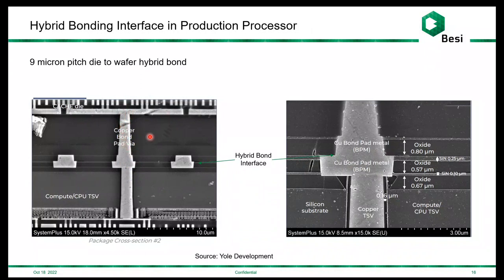This is a very thick passivation with a little bit smaller hybrid bond pad, copper bond pad. You can see that they're connected with very precise bonding. I would estimate this is less than 100 nanometer misplacement in this particular image. You can see a little bit more detail on this side. So from the scale here, this is 3 micron. The bond pad is roughly that dimension on the bottom side and a little bit smaller on the top side. And it's pretty well centered in bonding.